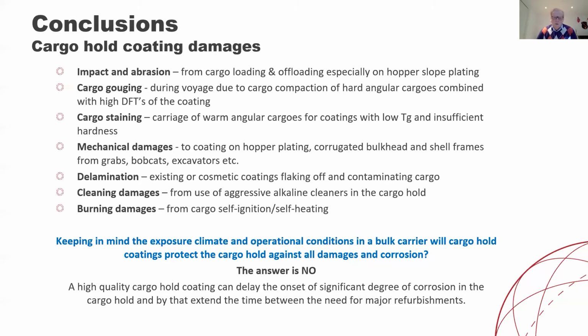So keeping in mind the exposure climate and the operational conditions in a bulk carrier, will cargo hold coatings protect the cargo against all damages and corrosion? Well, the simple answer there is no. However, as already pointed out by Sam from Jotun, a high quality cargo hold coating can delay the onset of a significant degree of corrosion in the cargo hold, and by that extend the time between the need for major refurbishments.